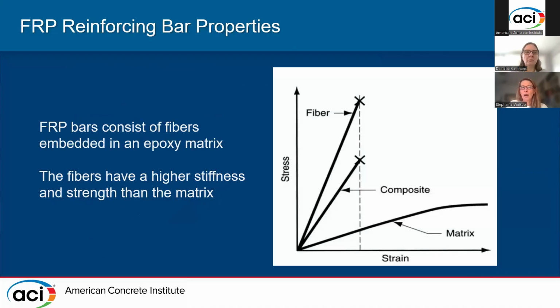In terms of the reinforcing bar properties, we're first going to break this down into the FRP fibers, and then also talk about the epoxy matrix, and then we'll see what happens when we put them together. If you take a look at the stress strain diagram, we can see that the fibers of the FRP bar are actually stiffer than the epoxy matrix. So when we combine the fibers with the matrix, we end up with a composite bar that has a softer or smaller modulus of elasticity than the fibers, but a higher modulus of elasticity than the epoxy matrix.